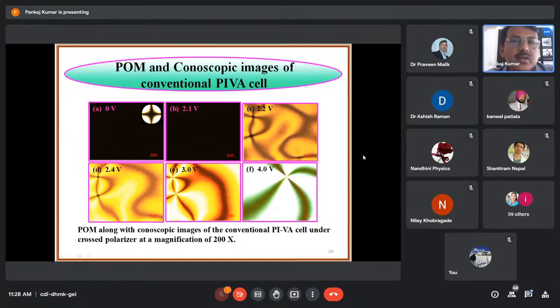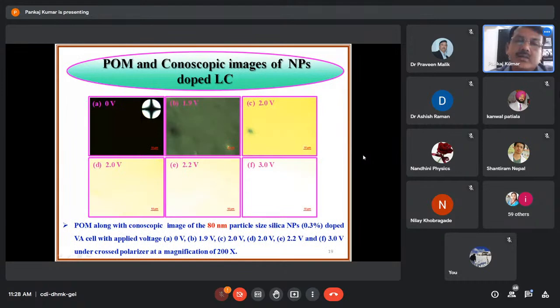But in figure C, figure D, figure E and figure F, you can see the images in the previous slides at 2 volt, 2.2 volt, 3.0 volt. It means that here the perfect bright state is there. It means that all the molecules are perfectly aligned in some particular direction.